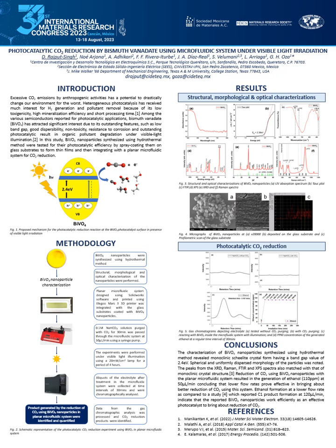For the results, first step was to identify the band gap energy of the nanoparticles, and based on UV visible spectroscopic studies, we found that the nanoparticles show good absorption in the visible light spectrum, and they showed a band gap energy of 2.4 electron volts, which is well reported in the literature.